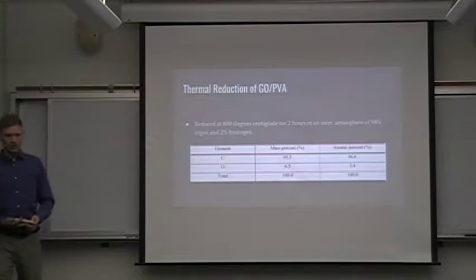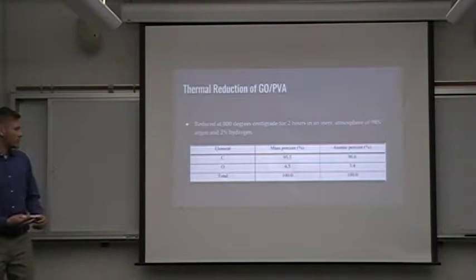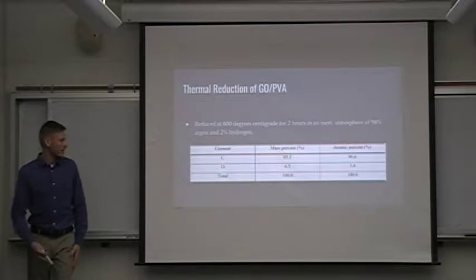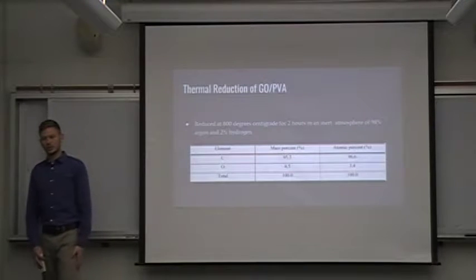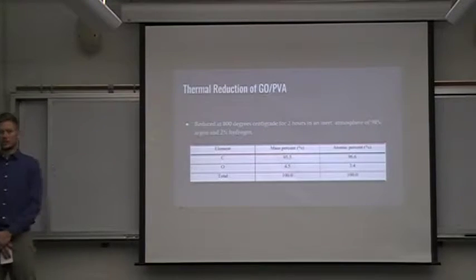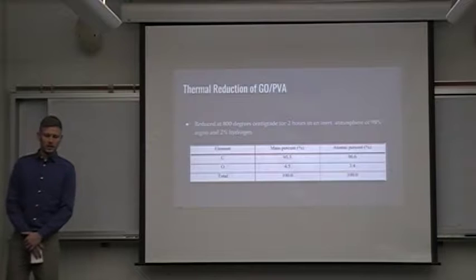The aerogel is then reduced, and this indicates that not all of the oxygen is removed during the reduction process. The reduction process takes place in an atmosphere of 98% argon and 2% hydrogen.